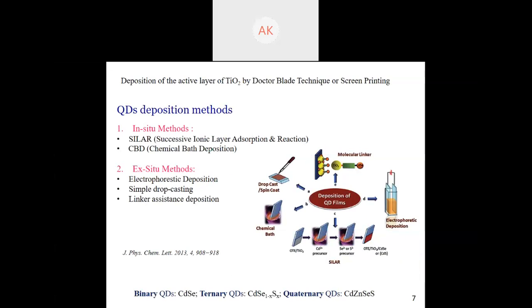Deposition of an active layer of TiO2 can be done by two techniques, either the Doctor Blade technique or a screen printing technique. And deposition of quantum dots can also be done by two techniques: the in situ methods and the ex situ methods. Now, in situ methods comprise SILAR, successive ionic layer adsorption and reaction, and chemical bath deposition. These methods ensure good contact between the metal oxide scaffold and the metal chalcogenide because they are growing in situ over the layer of the metal oxide.